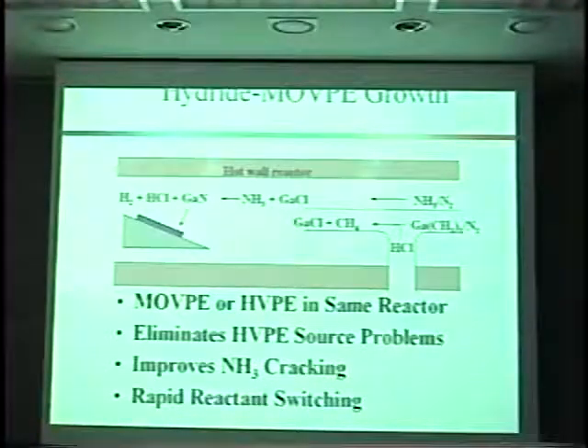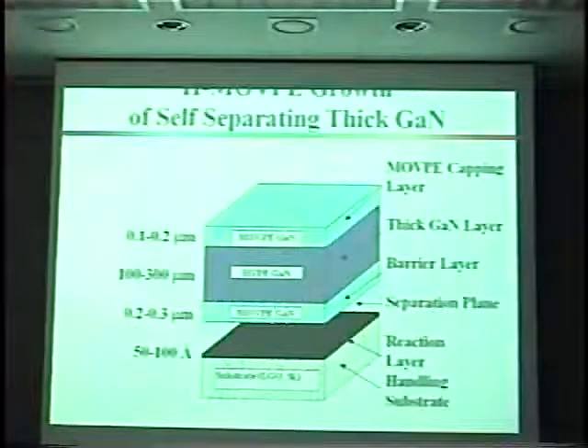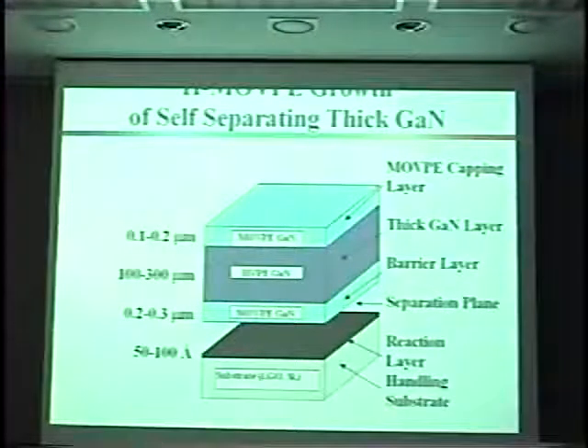That is, we can get rapid reactant switching, we can get clean sources, but at the same time we get the high growth rate of hydride VPE, and we also get the low impurity concentration advantage of having chlorine in the system. In addition, the HCl or the chlorine in the system helps lower the cracking temperature for ammonia and allows you to go a little bit lower growth temperature at the same quality and growth rate.